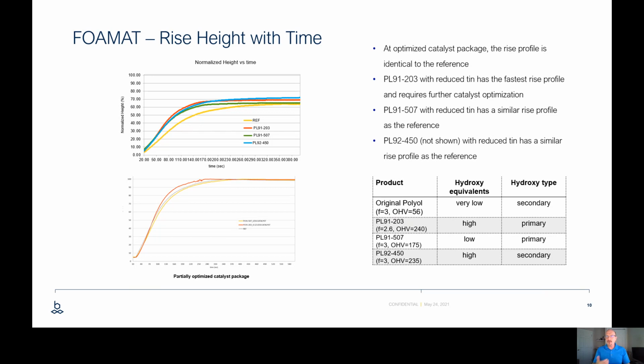The PL92-450, however, has a similar hydroxyl value as the PL91-203, so higher hydroxyl equivalent versus the original polyol, but now we have secondary OHs for those systems. So you can see that's why the reactivity is a bit faster for our materials, either high hydroxyl equivalents or the hydroxyl type is primary. We did do a small amount of evaluations, just a very small adjustment in the amine catalysts, and you can see they almost overlap with the control at that particular point. So these materials are fairly easy to modify the rise profile.